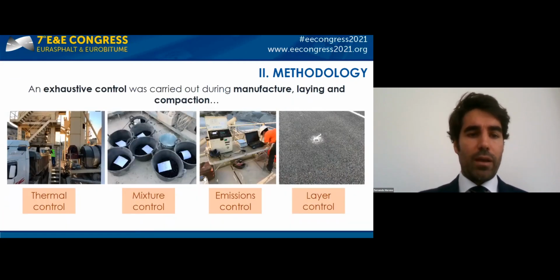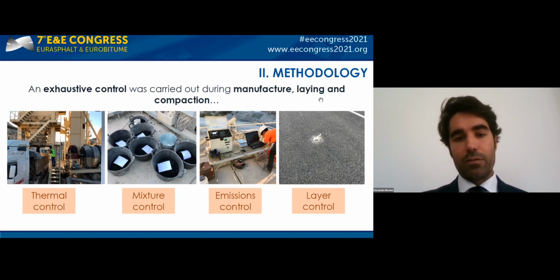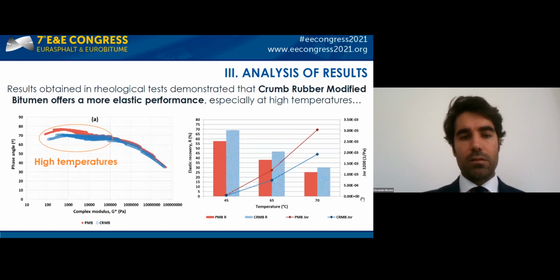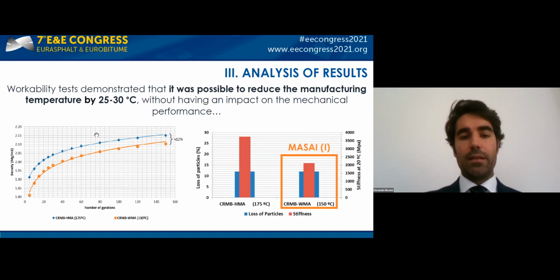After the construction of the trial section, we made an exhaustive control during manufacture, laying, and compaction that includes thermal control, mixture control, emission control, and layer control. Results obtained in the rheological test demonstrated that the crumb rubber modified bitumen offers a more elastic performance, especially at high temperature. The workability test demonstrated that it was possible to reduce the manufacture temperature by 25–30 degrees without having an impact on the mechanical performance of the material.